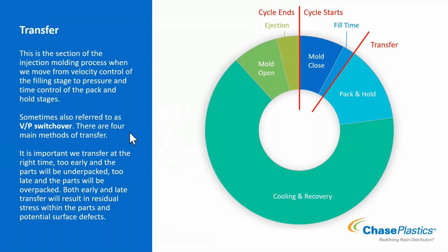It's extremely critical that we transfer at the correct position. If we transfer too early, we will likely underpack parts. If our packing velocity is lower than our fill velocity, we may see things like record grooving or hesitation banding appear on our parts. We might short shot. We might also drive a high amount of stress as we're getting a frozen layer building as we're trying to drive that polymer at a slower speed than through a constantly decaying flow front.